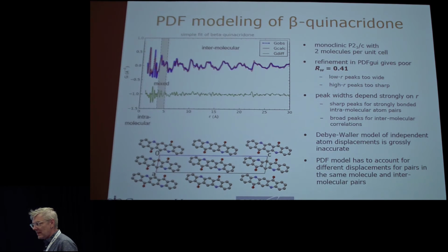Now, the molecule itself is covalent, so the bonding is very, very stiff. So the intramolecular peaks are very, very sharp. On the other hand, the intermolecular part, the bonding between the molecules is weak. It's van der Waals, or it might be hydrogen bonding. That's much, much weaker than the covalent bonding, which means that the peaks in the high R region are much broader because there's much more disorder and variability in the packing. Now, when you do crystallography, you don't actually see any of that because you only see the intermolecular correlation part.